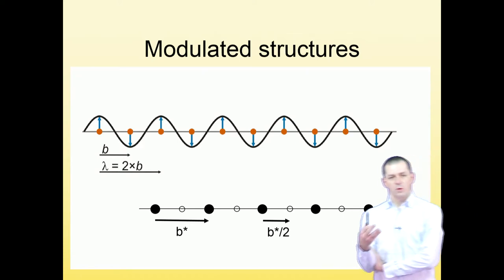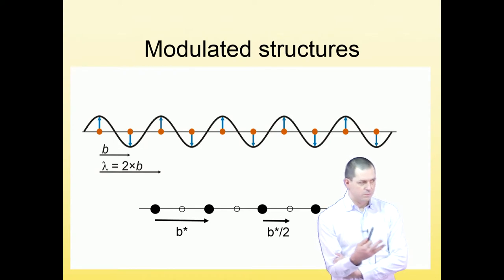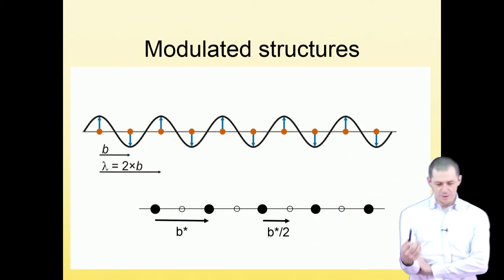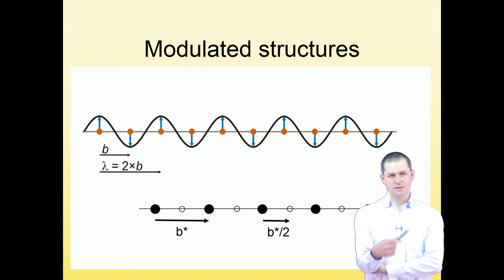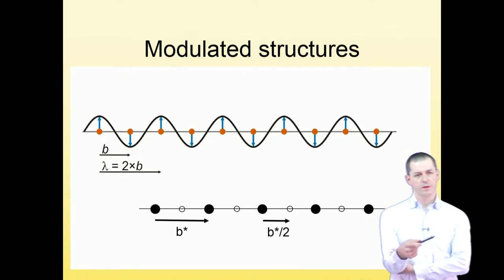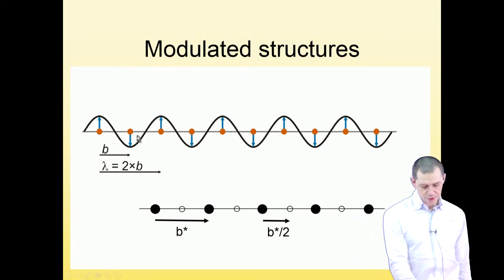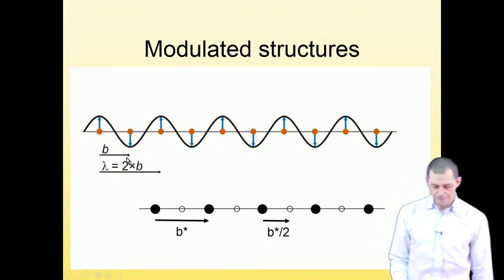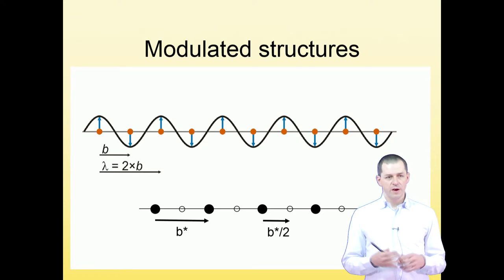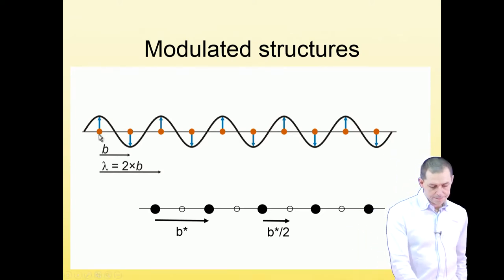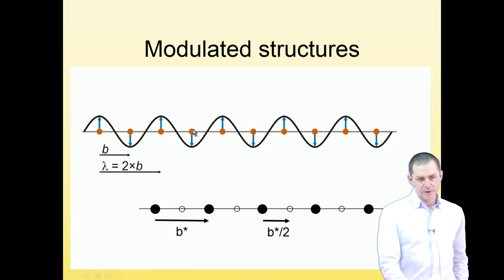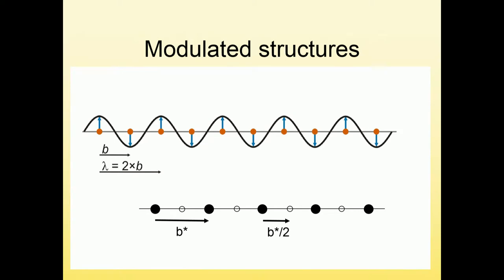So that's the diffraction pattern, but what does a modulated structure look like in direct space, in real space, in the structure itself? Let's first check a schematic simple structure with one atom periodically arranged in one dimension. So that would be this orange atom which repeats with a repeat distance B. And then you modify this structure by shifting the atom up and down and up and down. So in an alternating manner, shifting it in opposite directions. So then you generate a structure which will have a periodicity of 2 times B. This atom will be down, this up, this down, so there is no periodicity, and this goes up again.